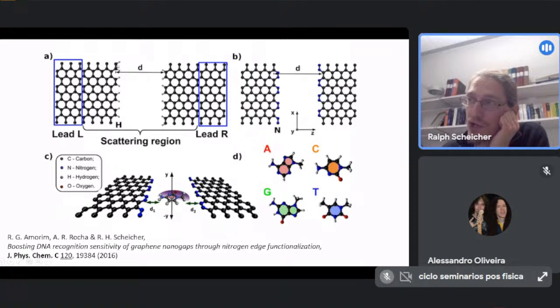The original paper there on this graphene nanogap, we had the graphene gap terminated with hydrogen atoms. So we had these dangling bonds here saturated with hydrogen atoms, but there are other choices. You can also saturate them with nitrogen, for example. And this is an approach that can actually result in an enhancement of the conductance of the system, and can also enhance the distinction between the 4 different DNA bases. So